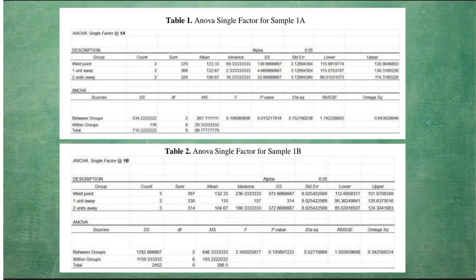So for table 1, we have a p-value of 0.0152, which is less than the alpha level of 0.05. Therefore, we reject the null hypothesis, indicating that the measurement location has a significant effect on hardness. For table 2, we have a p-value of 0.1057, which exceeds the 0.05 threshold. Therefore, we fail to reject the null hypothesis, concluding that the differences in hardness across the three measurements are not significant.